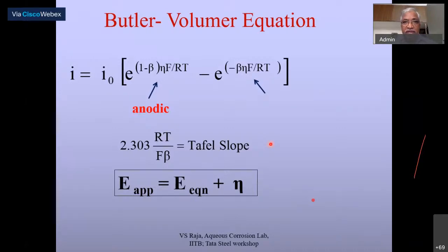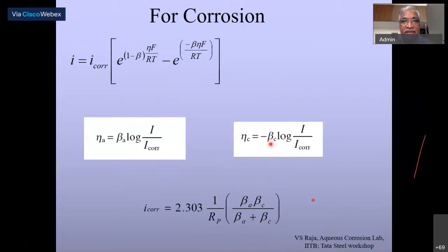And for corrosion, it becomes more complicated because in a corrosion process, as you've seen before, corrosion occurs not by one equilibrium, there are two equilibria, right? One is an oxidation, the other is a reduction process, and so we call them a mixed potential. That again, I'm going to skip the discussion of mixed potentials. So the corrosion potential and corrosion current is the result of net oxidation of the metal and net reduction of the environment, not the metal. The reduction is coming from the environment and oxidation comes from the metal.